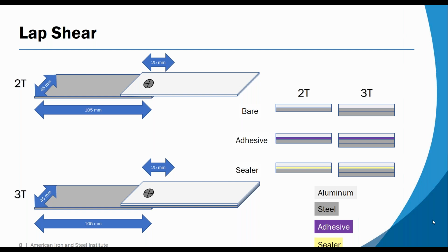But I mainly want to direct your attention to the 3 thickness joint configuration and the way that we applied the adhesive or sealers. In each case, we applied a structural adhesive or a non-structural sealer between the aluminum top sheet and the steel mid sheet.